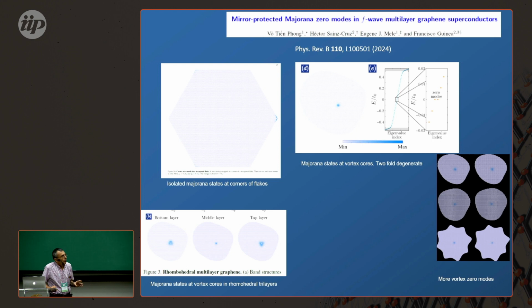Rigorously, f-wave superconductivity in a system with C3 symmetry is equivalent to L equals zero symmetry, which agrees with what Andrei Chubukov was telling us this morning. So I call it that, but it has different symmetries under different operations. S-wave is equivalent to no change at all under any symmetry operation, while this changes sign under some operations.